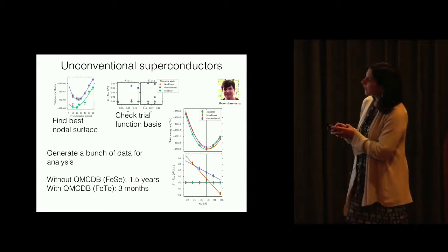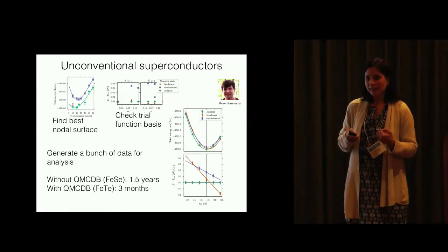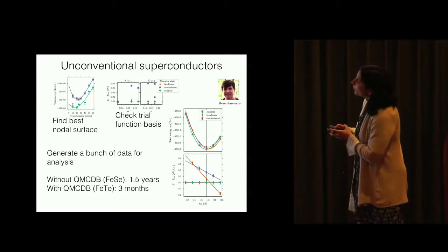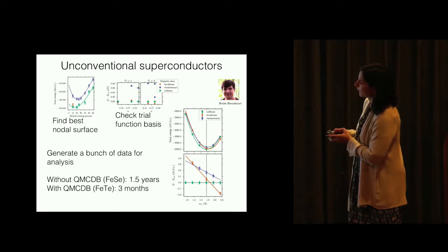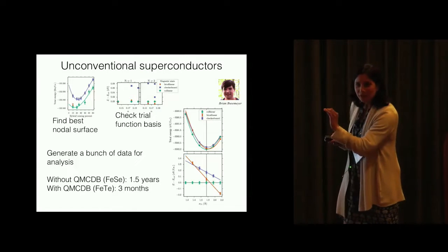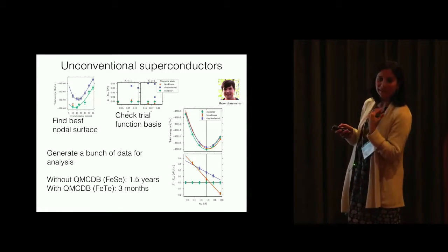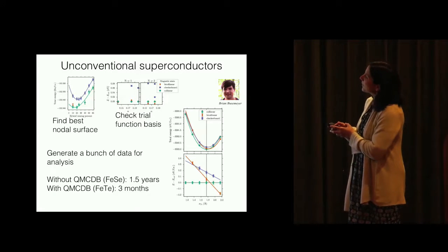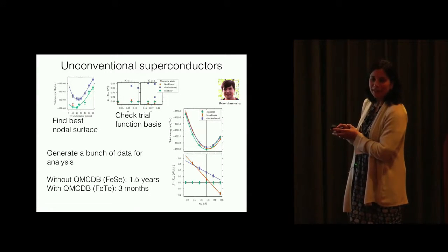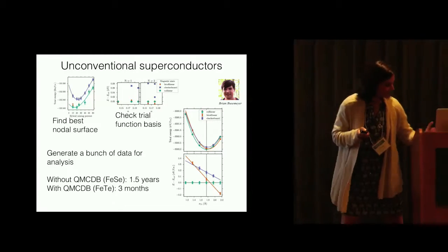What's being shown in these diagrams, I talked a little bit earlier about figuring out what it takes to actually get the calculations right. What we're showing here, for instance, is the total energy of the material as a function of, think about this as different trial wave functions and different starting guesses. Basically the idea is that since our technique is a variational technique, we can see which trial wave function gives us the best description of the actual material wave function here.